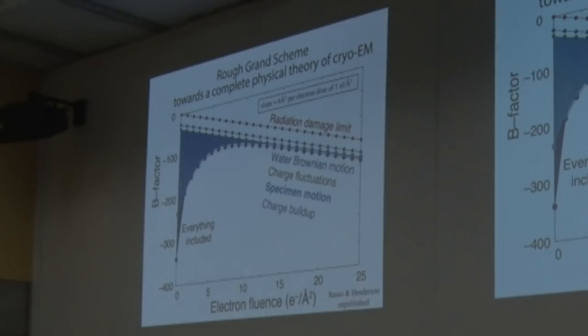The thing that, at the moment, is the rate-limiting one is this beam-induced specimen motion. When the beam comes on the specimen, the water molecules can move around, and then stresses that have been frozen into the specimen when you plunge-freeze it into the liquid ethane are released. And that's what we think is happening here. So something needs to be done, either to create a thin film that doesn't have stresses or to find a way of releasing it without doing radiation damage. So that's where we're at the moment.